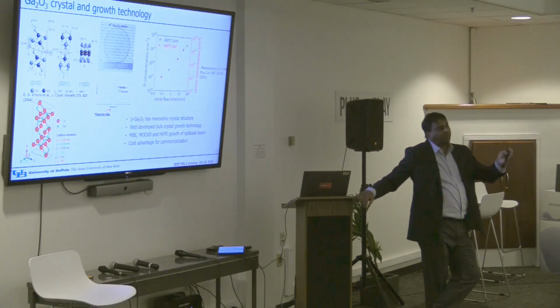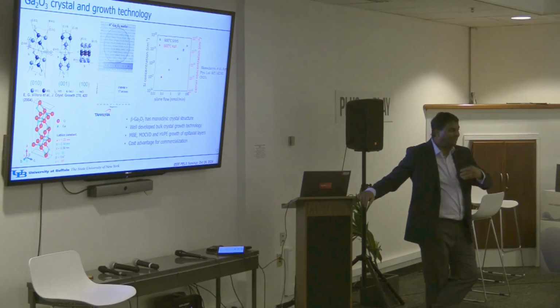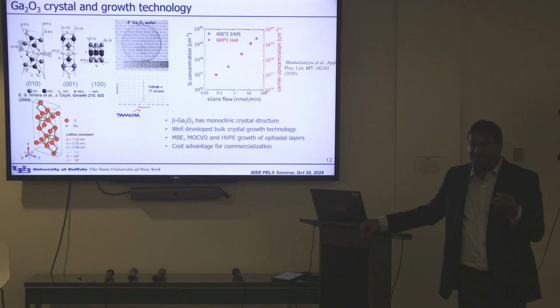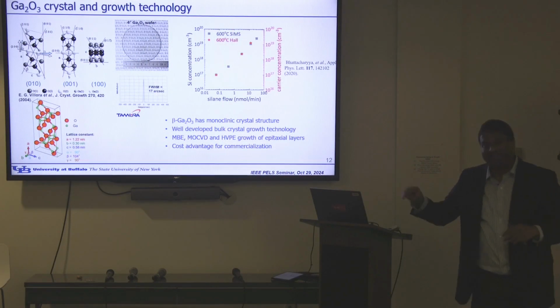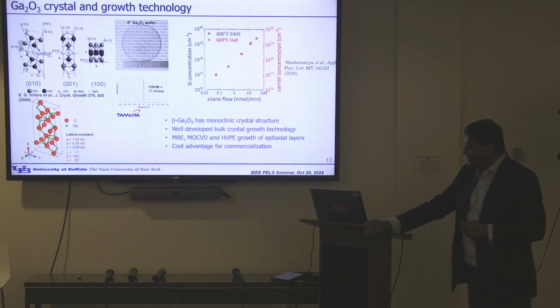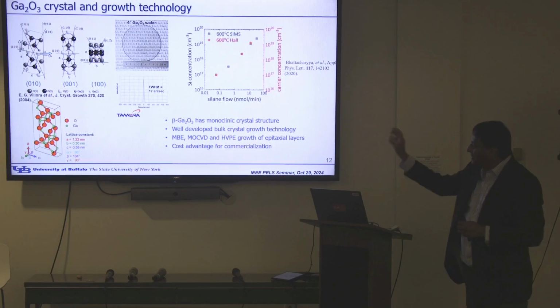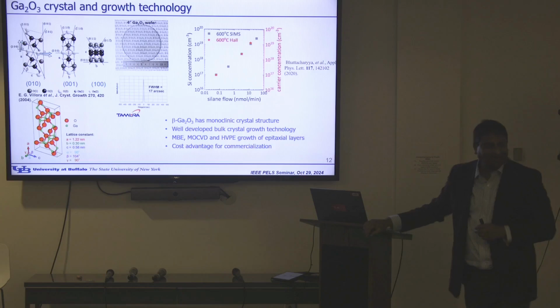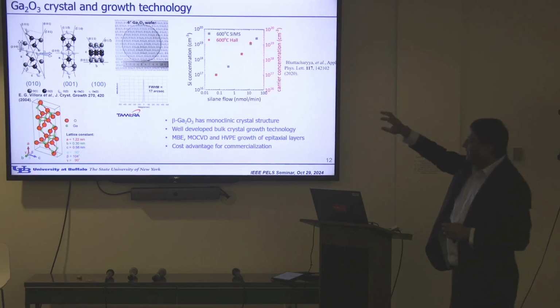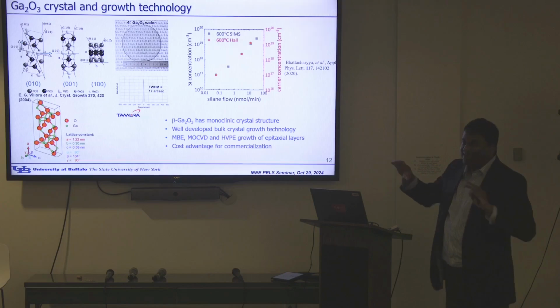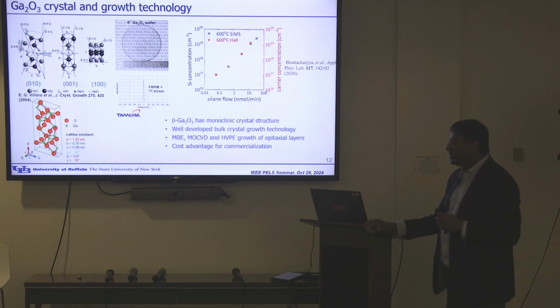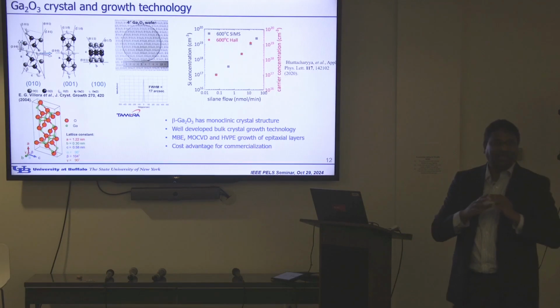Now, gallium oxide actually has 5 phases. Chemistry-wise, the beta phase is the most stable phase. I think people who may or may not know, silicon carbide has 100 phases actually. So that should not be a cause of concern, I would say. But this is the most stable phase. It's a monoclinic crystal again. If you recall your chemistry, you know a little bit on the crystal symmetry. It is anisotropic, so I would say for this audience, just don't worry about it. It has some impact on say contacts and other chemical processes. But the electrons are completely isotropic, right?